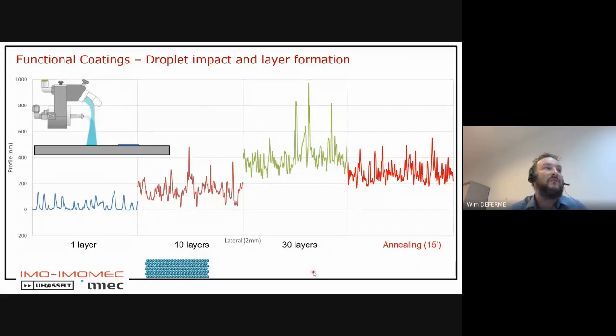However, because now you're not only talking about the droplets and the formulation of the droplet itself, the ink formulation, but you also talk about the substrate and the behavior at the surface free energy of your substrate. You also talk about flow behavior there. So you talk about Marangoni flows and coffee ring effects. What you get if you deposit is that these nanoparticles tend to move towards the edge of the ring, or move together and form these clusters. And then, of course, if you put 30 layers, you get this. So it's also about optimizing the impact of the droplets onto the substrate.